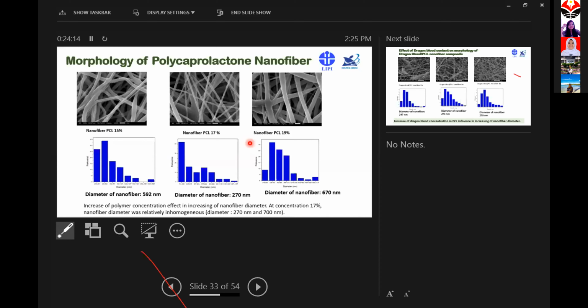We can make nanofiber without beads from concentration 15% to 19%. You can see that increasing the polymer concentration will increase the fiber diameter. This is related to the effect of the viscosity of the polymer solution.